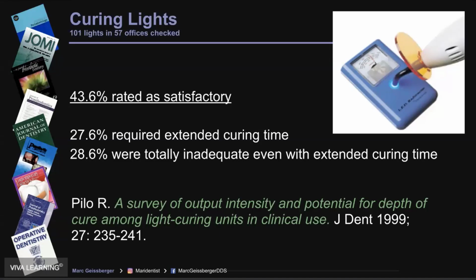So the Journal of Dentistry published this article by a young practitioner who went into 57 dental offices in their practicing area, meaning around their community, and just asked the docs if they could test their curing lights. So during the study, the clinician tested 101 curing lights. Now, keep in mind, this is 1999. We weren't using LEDs, we were using halogens. But what this practitioner found was that only 43% of the lights that they tested rated satisfactory for curing at the prescribed curing length of time. And at the time, that was 40 seconds per 2 millimeter increment.